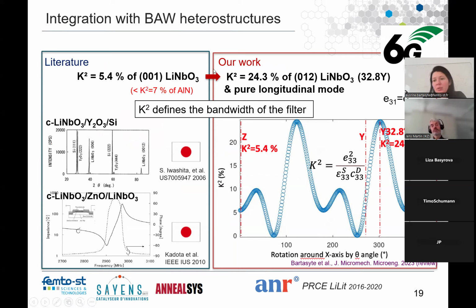And then what we proposed is to grow 32.8Y-oriented lithium niobate or 012-oriented lithium niobate, which offers a material coupling of 24.3% for the longitudinal wave. And it also offers a pure longitudinal wave. So if we look here, it's the maximum which is possible for lithium niobate for the longitudinal wave.